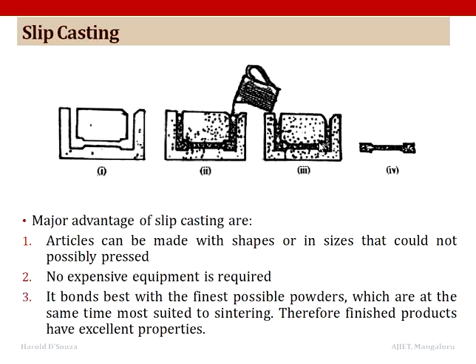The success of the slip casting process depends on the rheological as well as the casting process of the slip. The important factors affecting the above parameters are the type of material, the size and the surface area of the powders, pH of the slip and additives that are being used. In addition, processing conditions such as mixing, casting rate and processing temperatures should be kept uniform to achieve consistent quality of the product. Now a major advantage of slip casting is that articles can be made with shapes or in sizes that could not possibly be pressed. No expensive equipment is required and it works best with the finest possible powders which are at the same time most suited for sintering. Consequently the finished products have excellent properties.